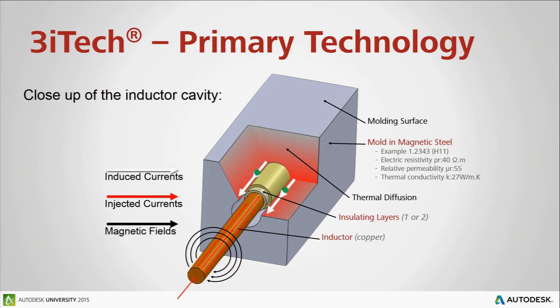It's not an empirical approach where we make a tool to find out if we can make a good part. No, we design an induction network that is relevant, that is proven, and then we work on the tool design with the tool maker. We do not heat the surface of the tool directly with the magnetic field. We heat the inner portion of the channel, and then by conduction, we heat the surface.